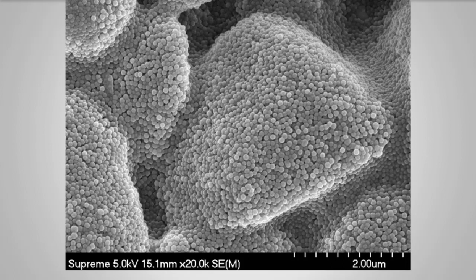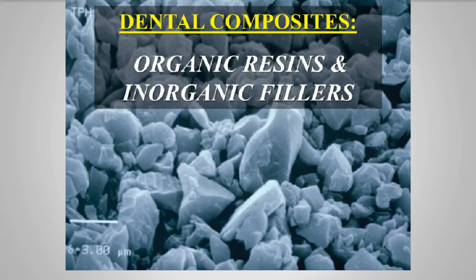But the fact is, most composites still use significant amounts of ground glass in their formulations. And this is what some of these glass filler particles typically look like under a scanning electron microscope. They come in various shapes and sizes, and they're generally made of ground silicate glasses of some type. Barium silicate is particularly popular today because it's relatively easy to produce, has very nice physical properties, and has a nice radiopacity, so it's easy to see on an X-ray.